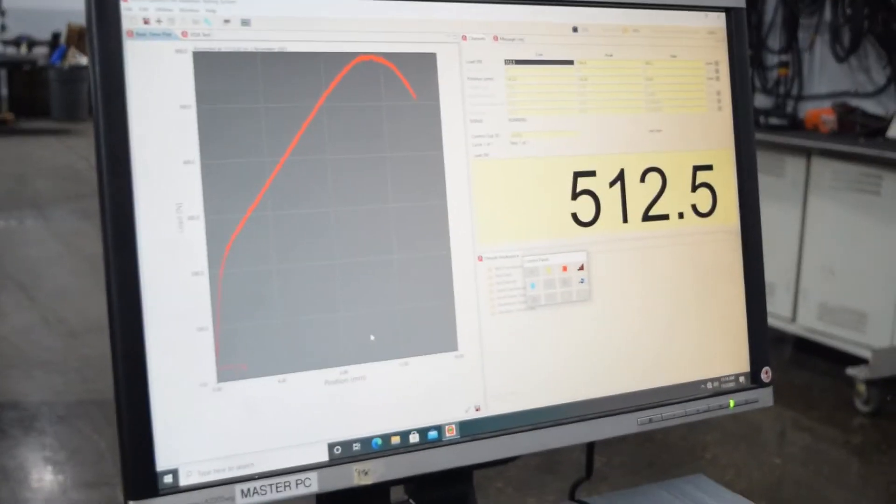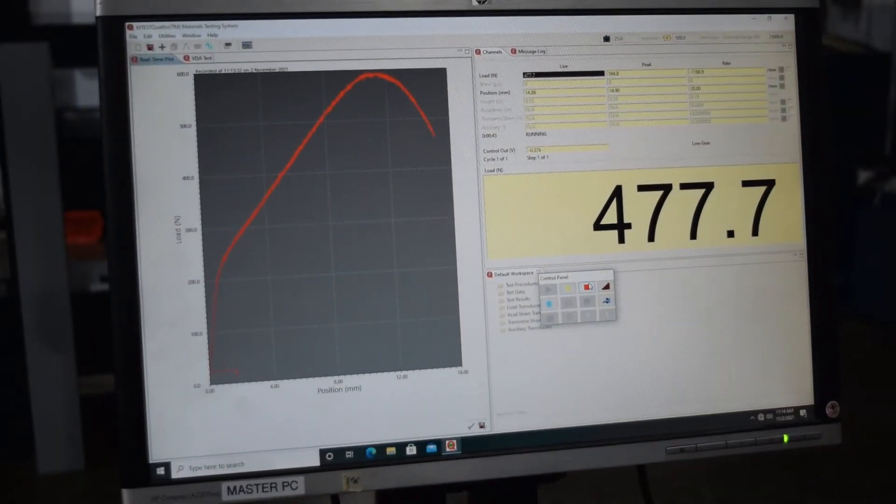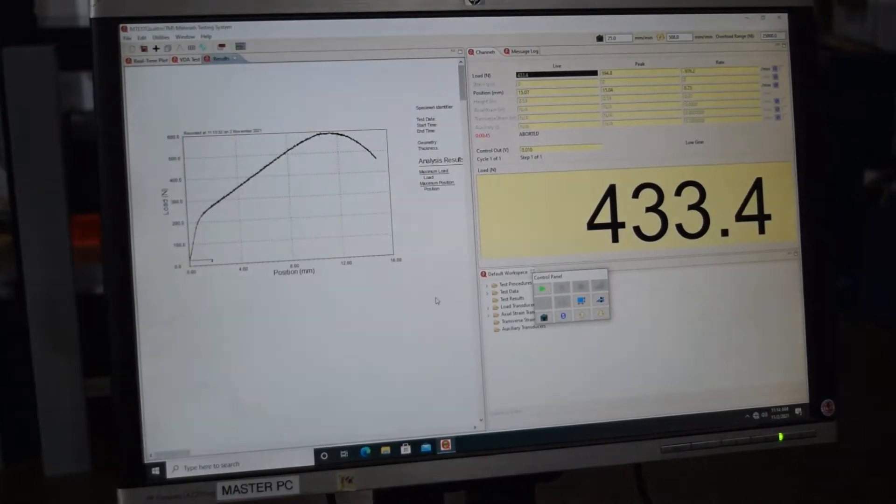At this point, we're losing load. Now that we have lost more than 60 newtons, I can stop my test.